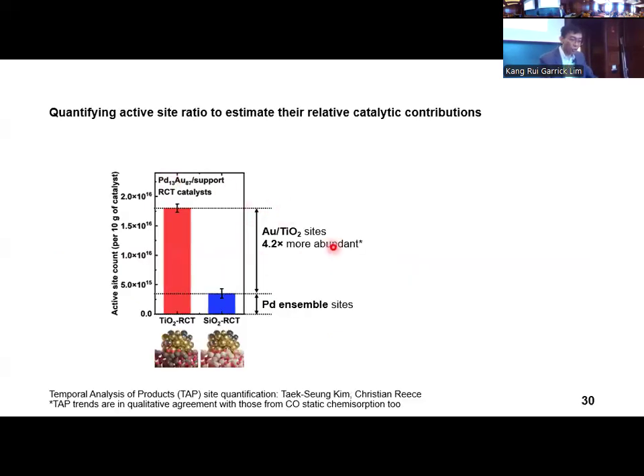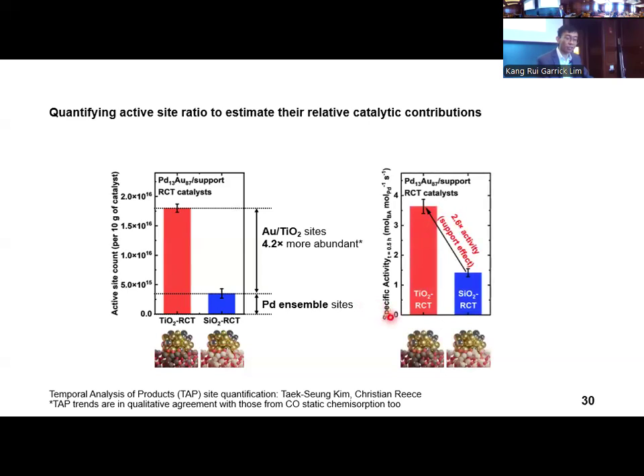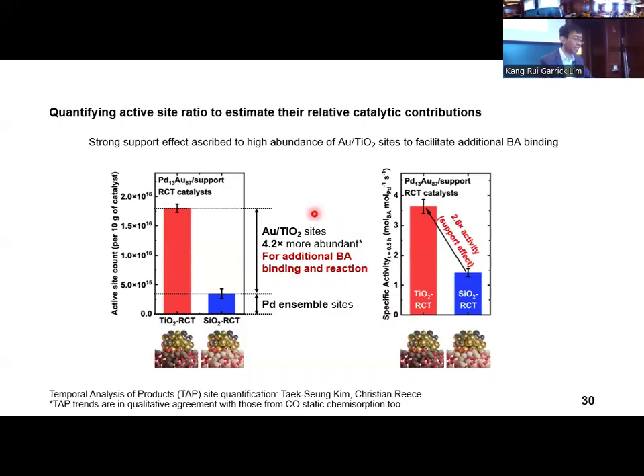As benzaldehyde binds to both the gold titanium interfacial sites and the palladium ensembles, we quantified the ratio of these binding sites to estimate their relative contributions to their catalytic activity. In the titanium-supported RCT catalyst, the number of gold titanium interfacial sites was 4.2 times higher than that of the palladium ensemble sites. Strikingly, this site counting result parallels our activity results earlier. Thus, we attribute the strong 2.6-fold activity enhancement primarily to the high abundance of gold titanium interfacial sites, which was created by partial nanoparticle embedding to facilitate additional benzaldehyde binding in the titanium-supported catalysts.